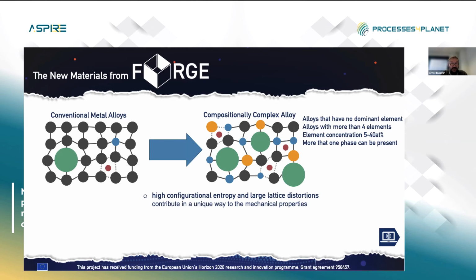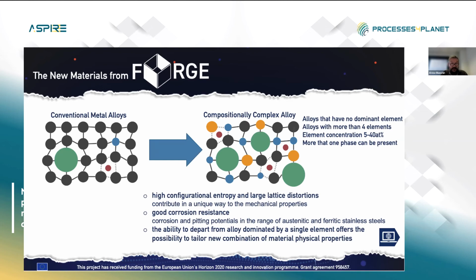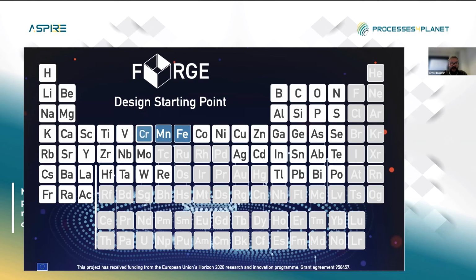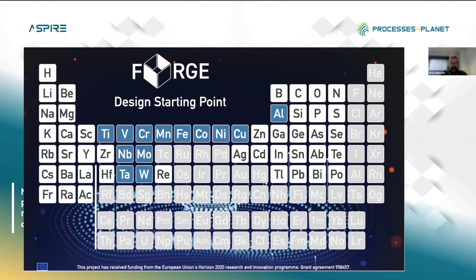We are using compositionally complex alloys as the framework for high configurational entropy, which can provide unique mechanical properties, but also good corrosion resistance, and the possibility to tailor new combinations of materials and be more flexible on the specific uses of the materials. In order to identify a good compositionally complex alloy, we need to constrain ourselves to some elements to be included in this scenario. And in Forge, we identify these elements, removing those that are less usable or not really worth considering at the moment.